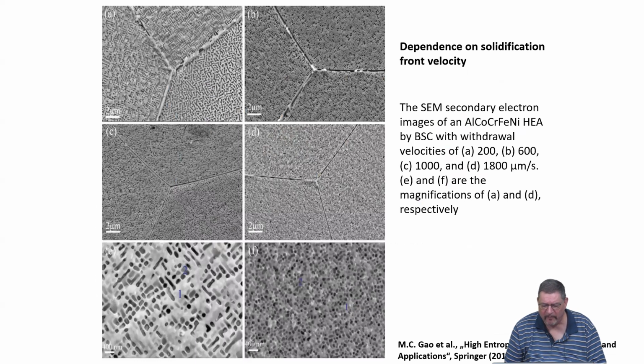So depending on how fast you pull in this Bridgman solidification casting, you get in this high entropy alloy different patterns of the microstructure, and you see that the faster you pull, and D would be the fastest, you get the finest microstructure, because basically you allow the least time for the material at the high temperatures to form the local structure. It depends really on the alloy what you have to do, because sometimes you want these features to be larger or smaller, and then you can play with the solidification front velocity in this Bridgman solidification to obtain the microstructure which you like to have.